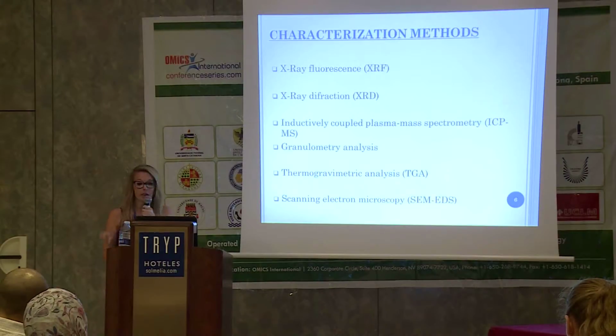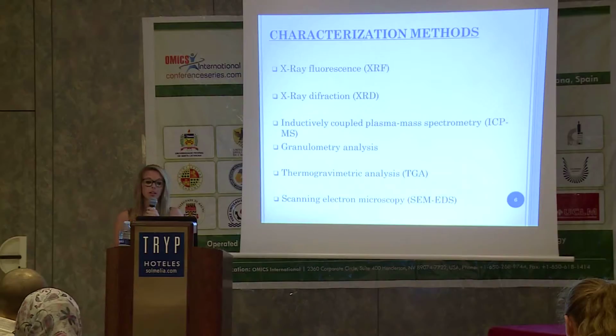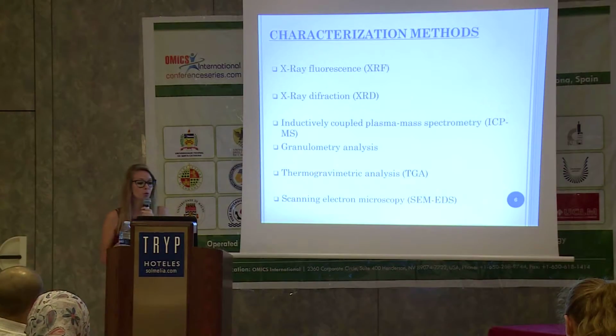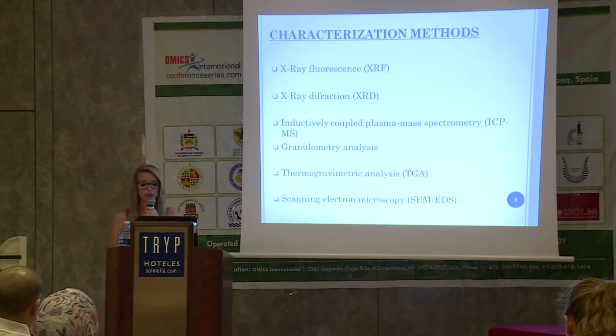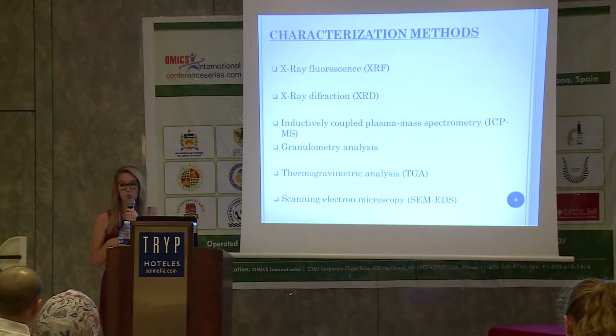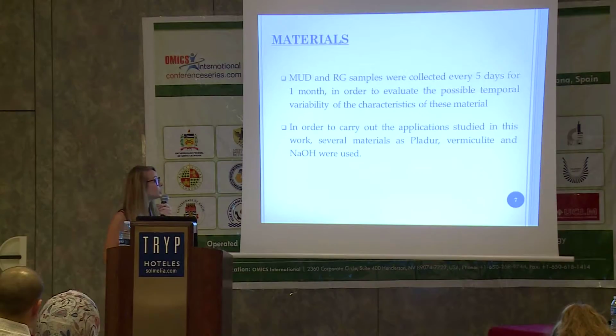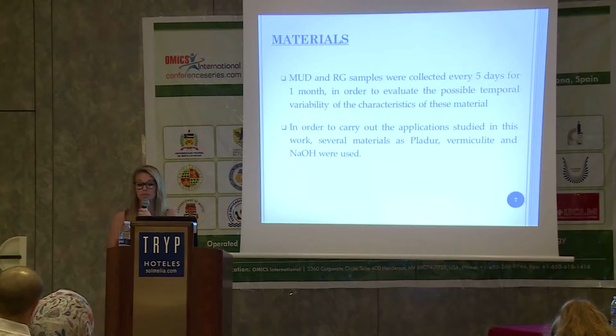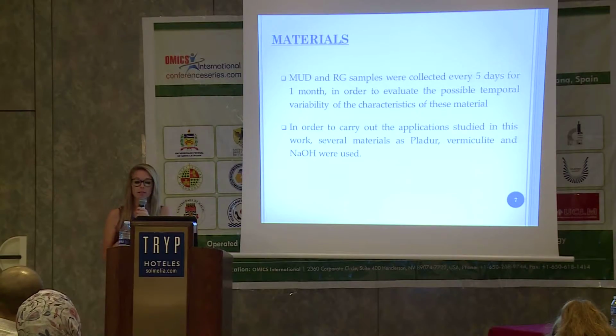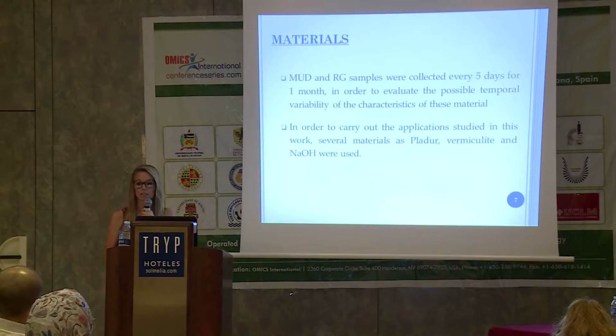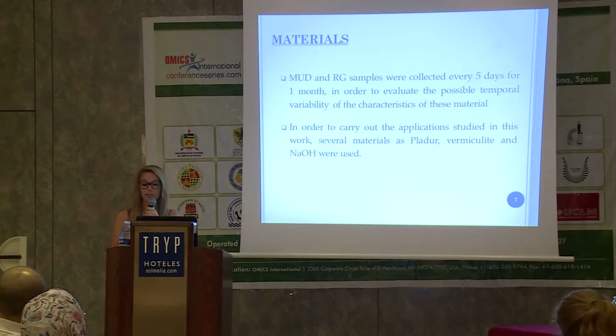In order to characterize the wastes and new products, the analysis techniques used were X-ray fluorescence, X-ray diffraction, inductively coupled plasma mass spectrometry, granulometry analysis, thermogravimetric analysis, and scanning electron microscopy. Mud and red gypsum samples were collected every 5 days for 1 month in order to evaluate the possible temporal variability of the characteristics of these materials. And in order to carry out the application study, several materials such as pladur, vermiculite, and sodium hydroxide were used.